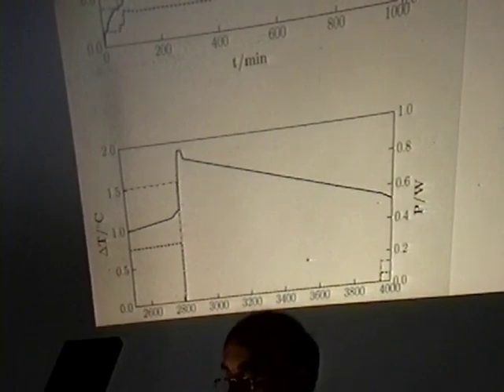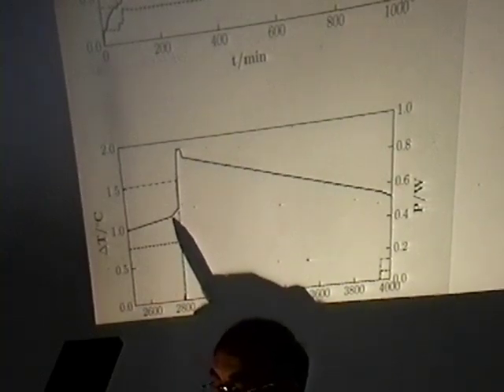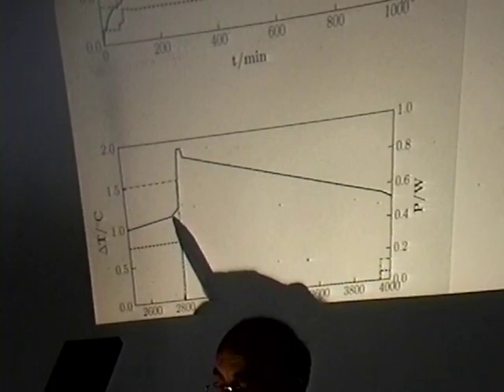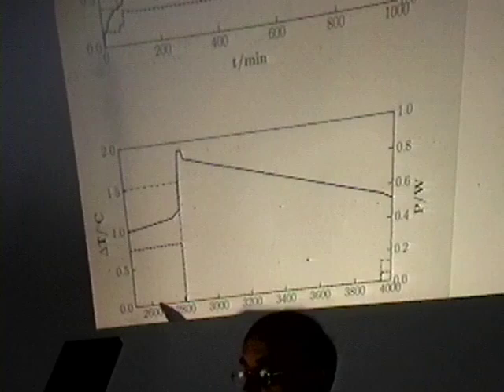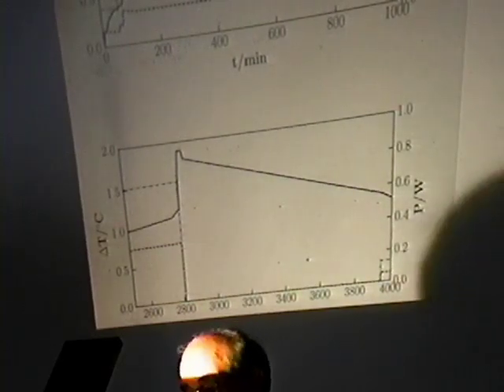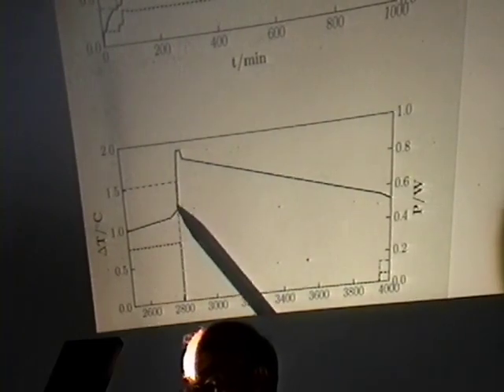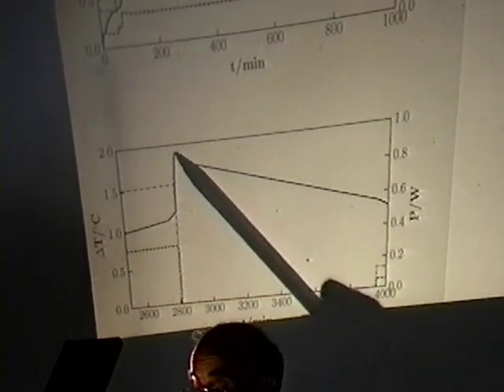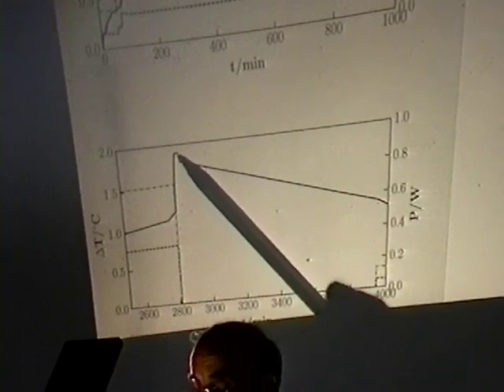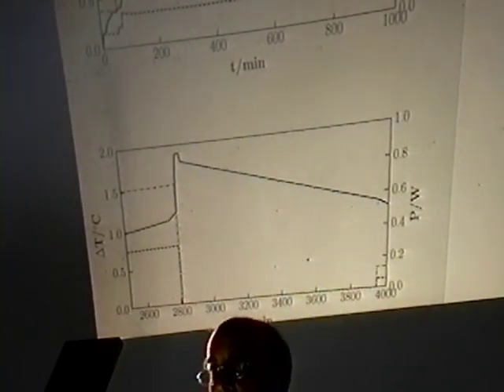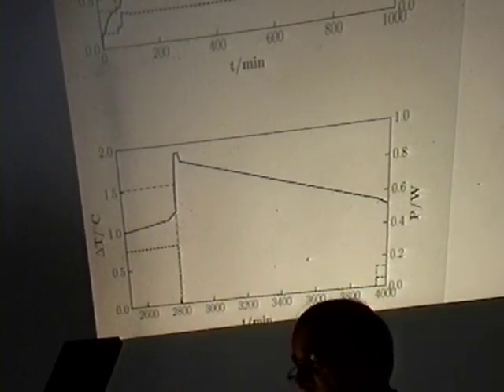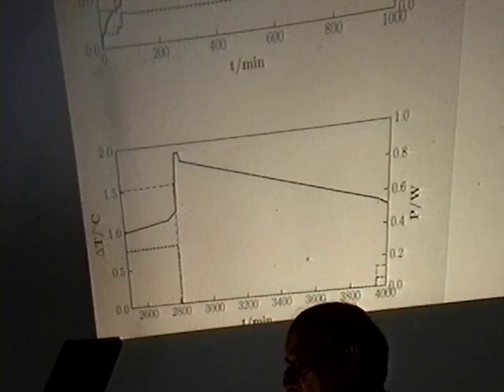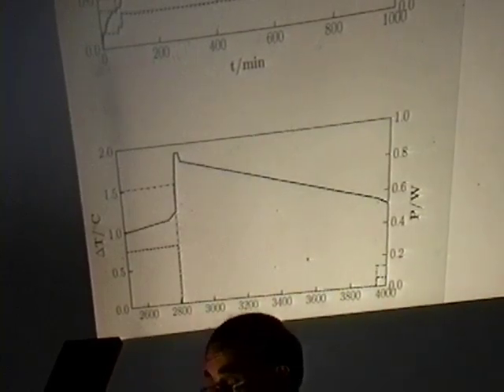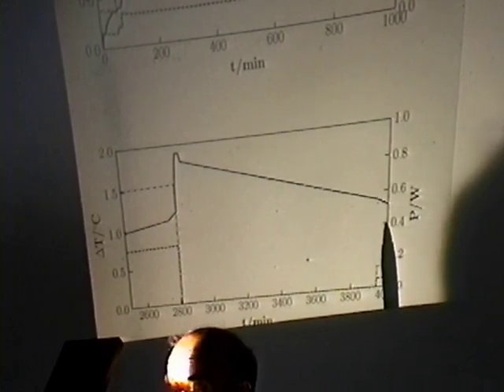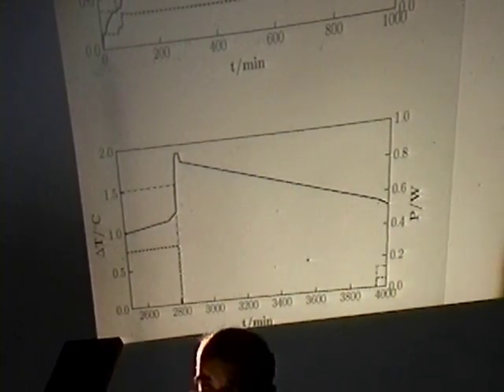After 2,800 minutes since the beginning of the electrolysis, about 2 days, we observed a trend to a steep increase in the temperature, and we became obsessive, observing this phenomenon. The temperature was increasing, reaching a maximum, and after that it was not relaxing according to the thermal heat loss of the cell. After more than 1 day, we applied current again.